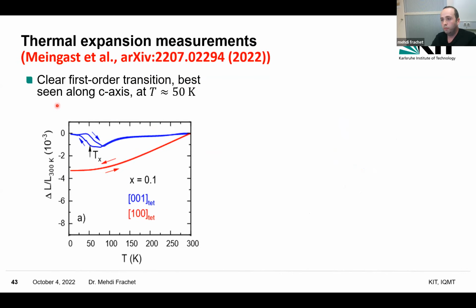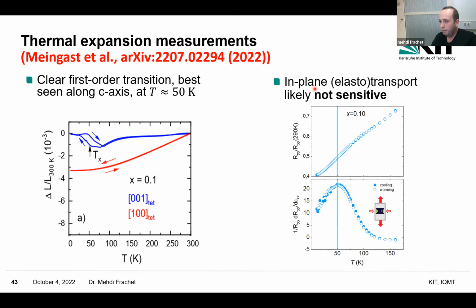The last thing I would like to mention is additional thermal expansion measurement in this sample. You can see the thermal expansion along the 100 axis in red and along the C axis in blue, and you see that there is a clear first order transition, which was seen by high resolution thermal expansion close to 50 Kelvin. Okay. We are still investigating what it is about. Actually, we still don't know exactly. I've looked deeply at the in-plane transport and elastotransport, and you see that there is no evidence for any hysteresis. So this transition is likely not directly related to this maximum of the elastoresistance, but we are still working on it.